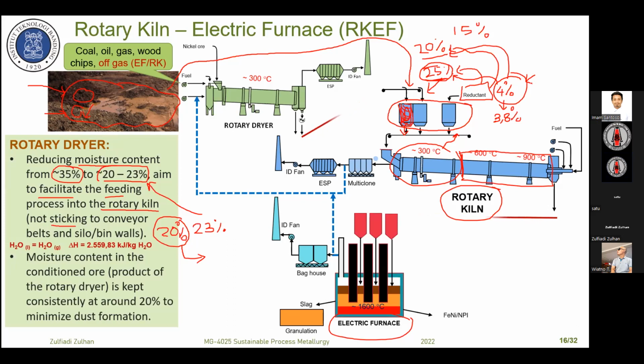For sure, at the end, in this case we have more carbon. In this case, we have less carbon. It will impact the product from the electric furnace. If we add more carbon, it means the carbon also reduces iron oxide, so we have lower nickel content in the product. If we add less carbon, less reductant, we get high nickel content. But in this case nickel recovery is low. In this case, nickel recovery is high.